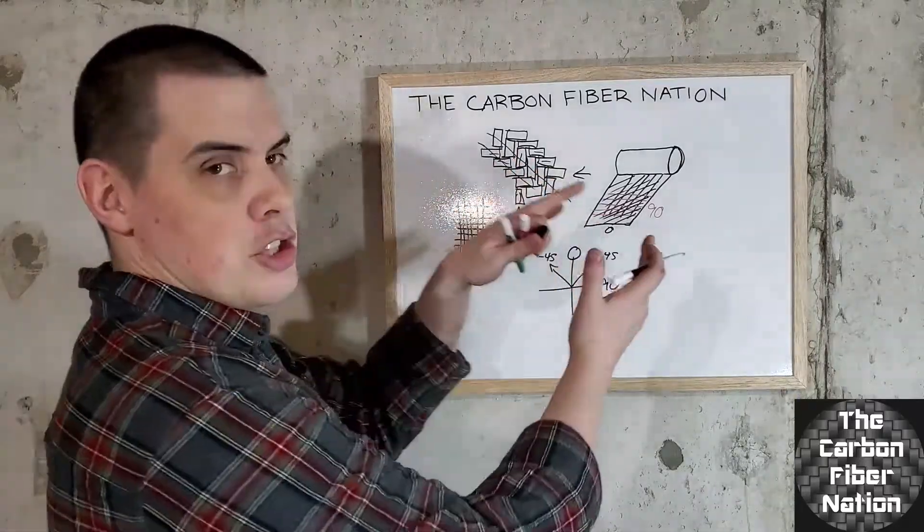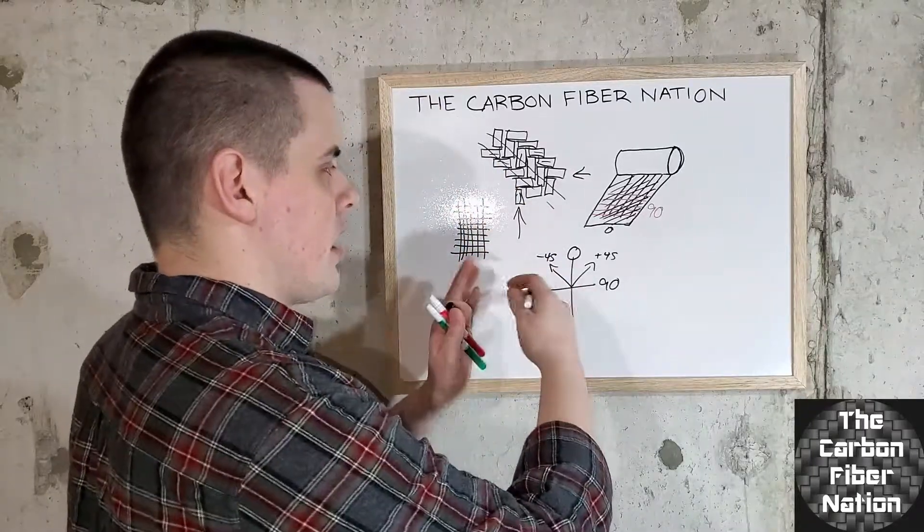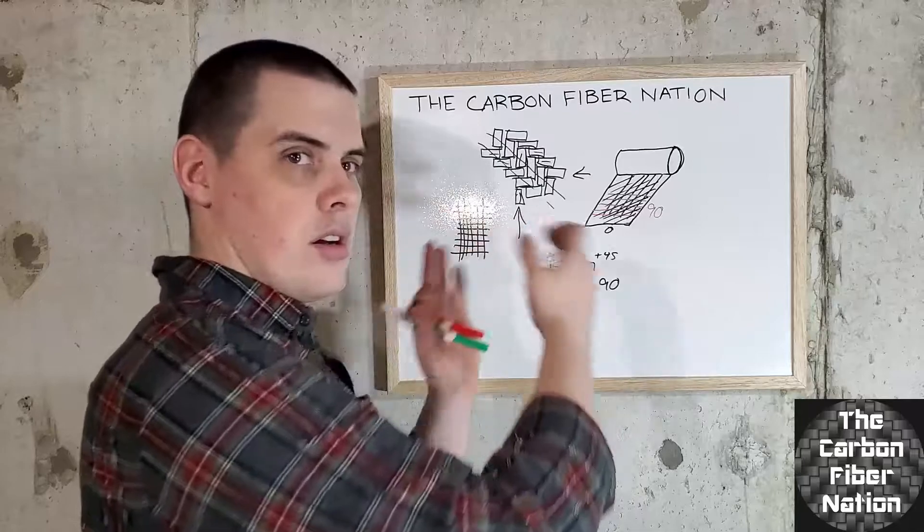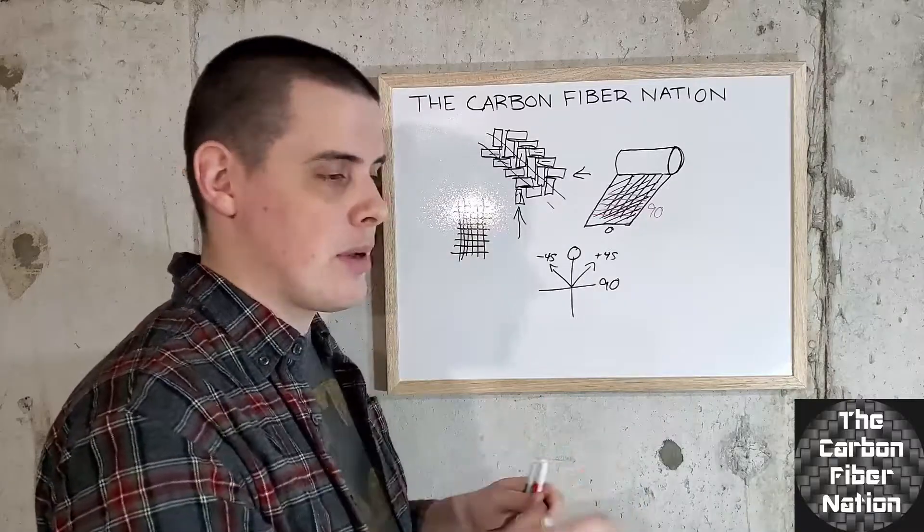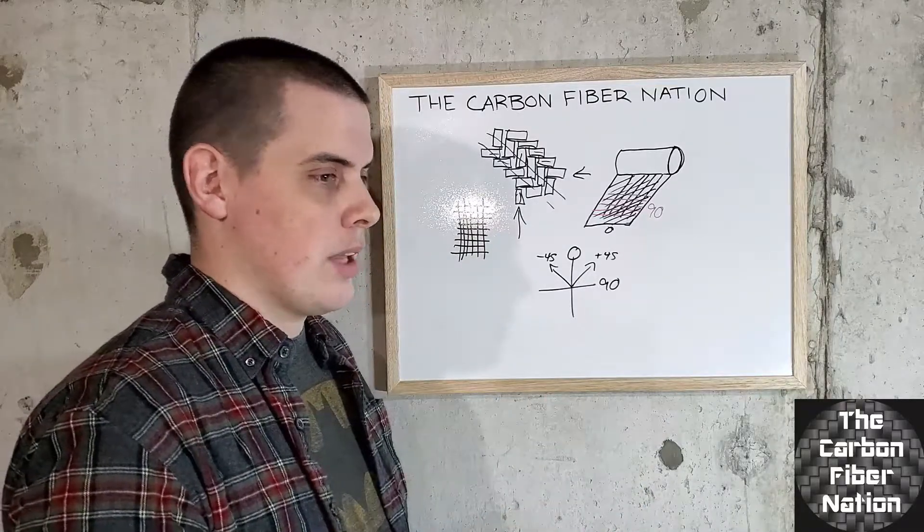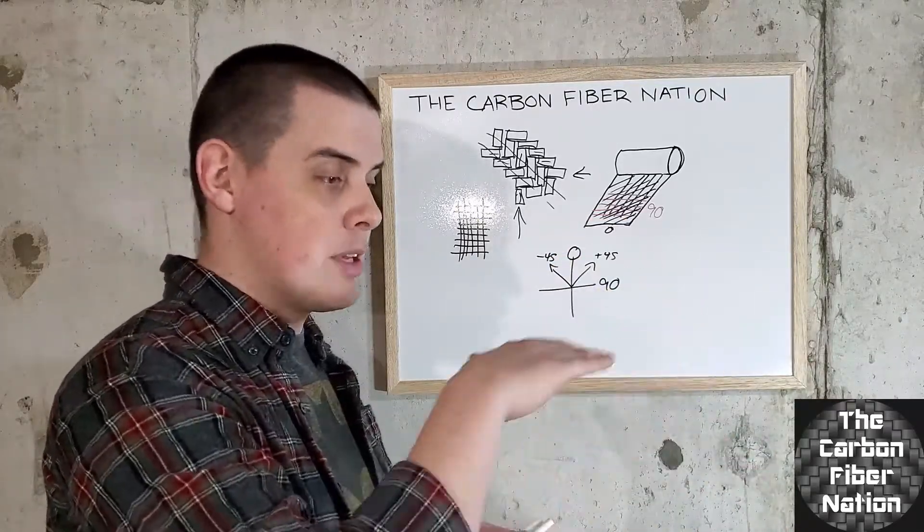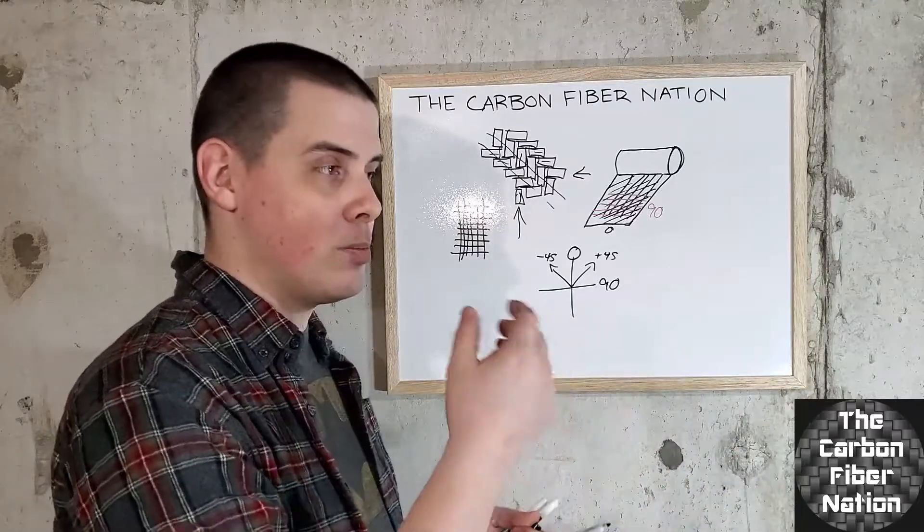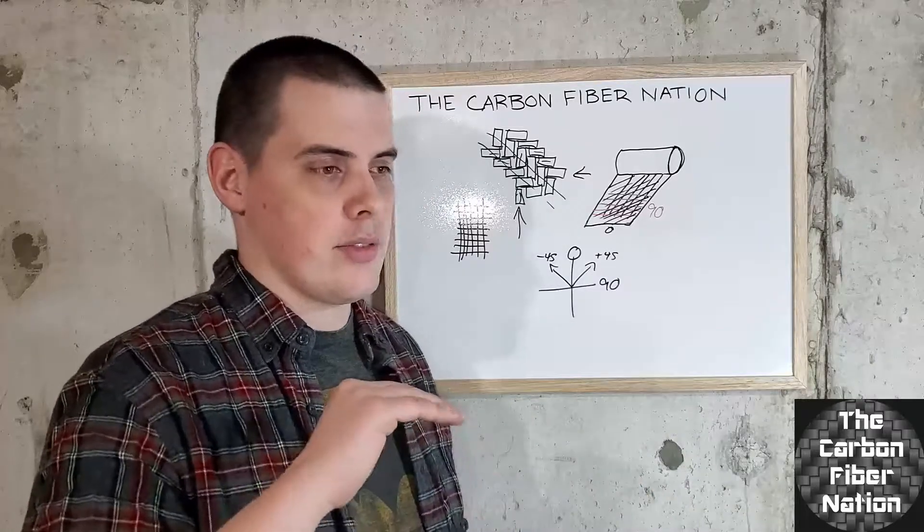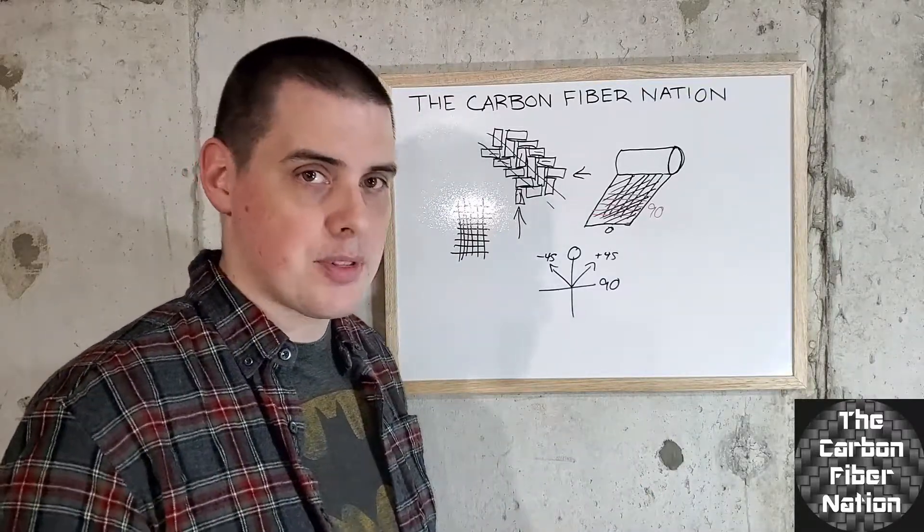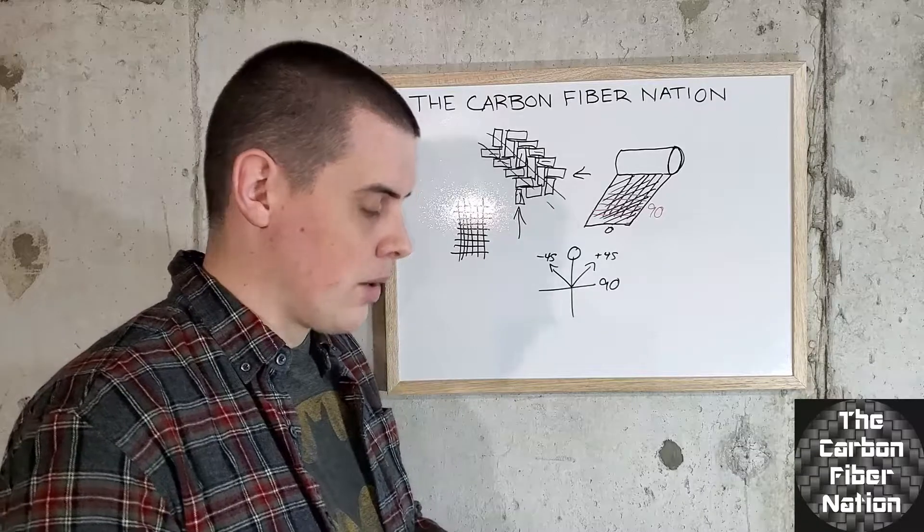This denotes if you're actually going to change the orientation of the fabric, not the pattern direction. This will say whether when you're laminating if you orient it on a zero and 90 or a plus minus 45. The plus and minus 45 really matter when you're doing like a big flat sheet with a complex layup of many layers. What you have to do is make sure that at the middle point of the laminate you switch it around to be the exact opposite, otherwise you'll actually get it to bend. We'll be covering more about balanced layups and flat plates and bending fibers a little bit later.